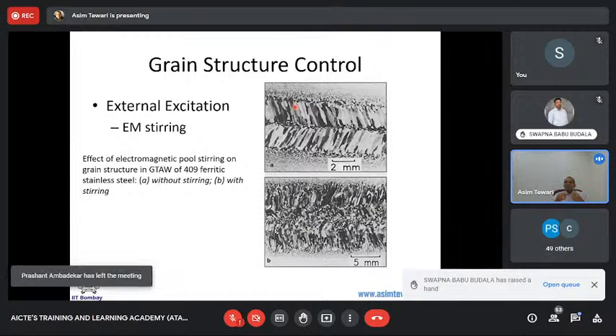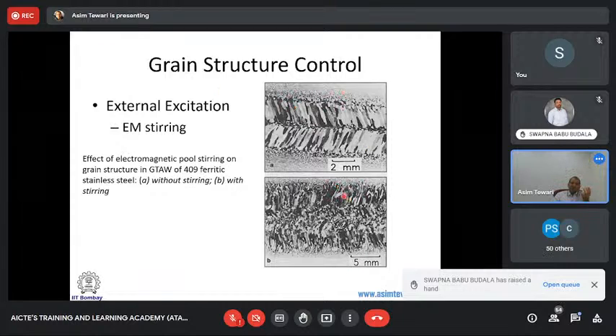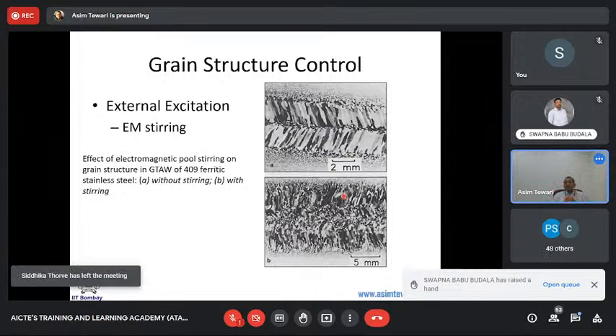So additive manufacturing is still a very big growing science. You are not just doing things by adding layer by layer, but you can do many other things around it at the same time. And one thing you can do is create stirring in the melt pool at the time of additive manufacturing. This shows that on the top, you have no stirring, and in the bottom, you add an electromagnetic field to stir the liquid metal in the melt pool while doing the additive manufacturing. Now, this has phenomenal potential for additive manufacturing.